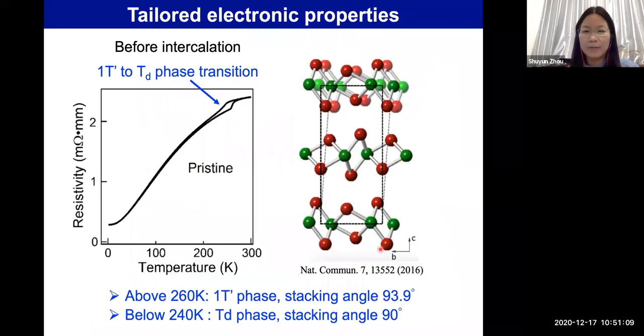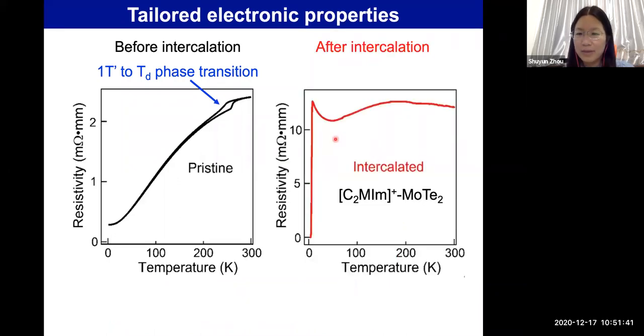Now, let's also look at other properties. Before intercalation, we know that this molybdenum ditelluride has a 1T prime to Td phase transition at about 240 to 260 Kelvin. This phase transition basically changes the stacking angle between the layers from 93.9 degrees to 90 degrees. Now, when we increase the interlayer spacing, let's see what happens. Here I show you the resistivity measurement as a function of temperature after this intercalation. And here you will see that after this intercalation, this phase transition is non-detectable. It's probably not too surprising when the interlayer spacing is so large and the interlayer coupling is so weak. The stacking doesn't really matter, and so this 1T prime to Td phase transition disappears.